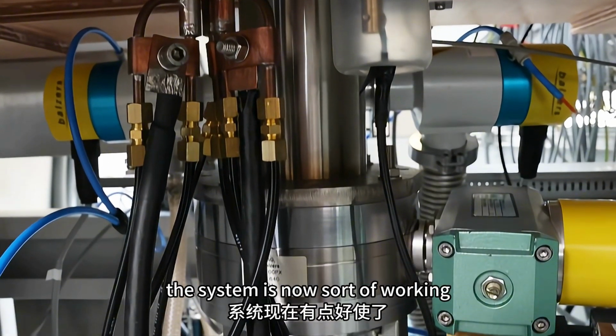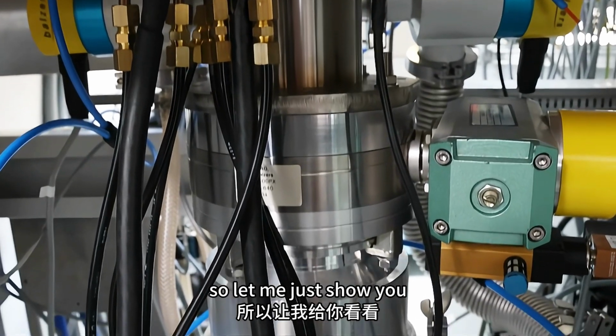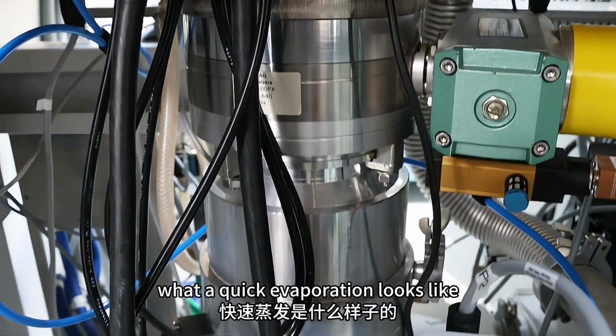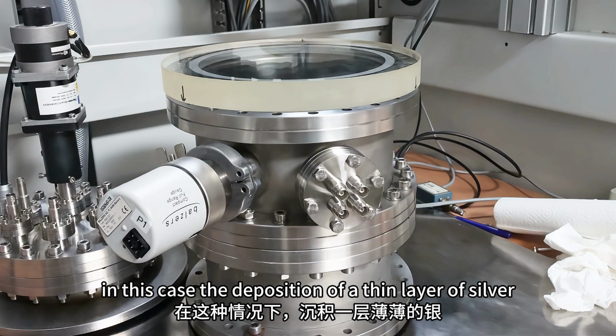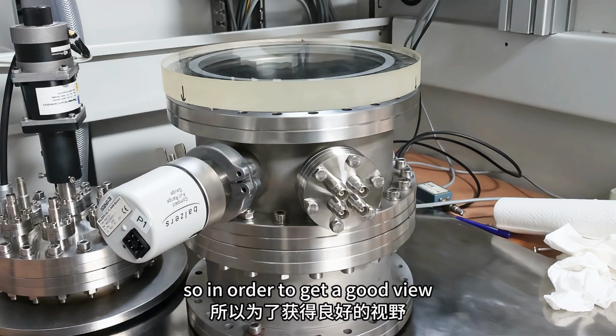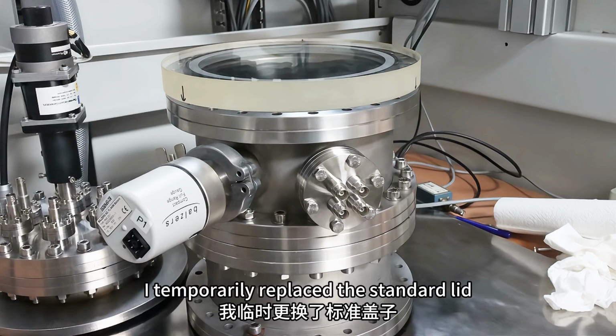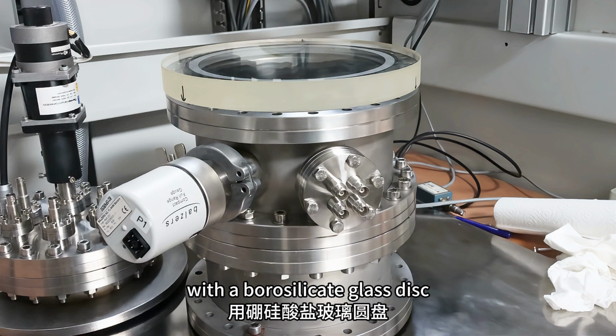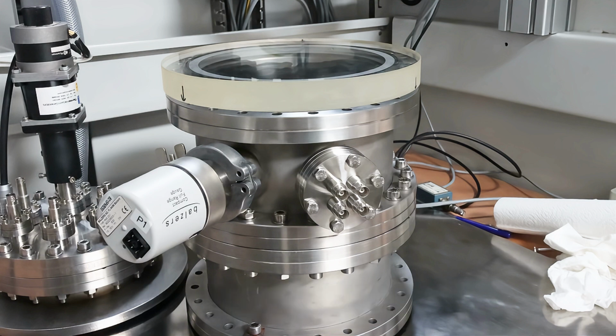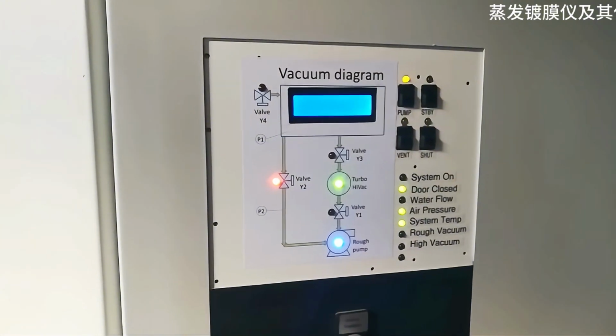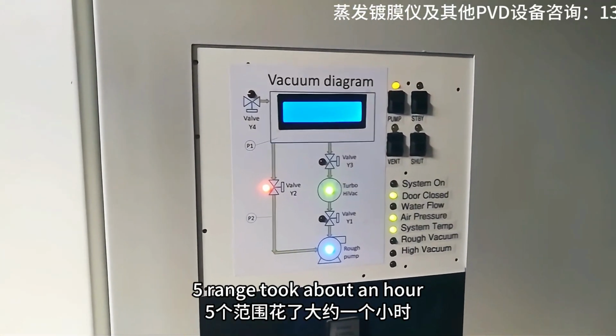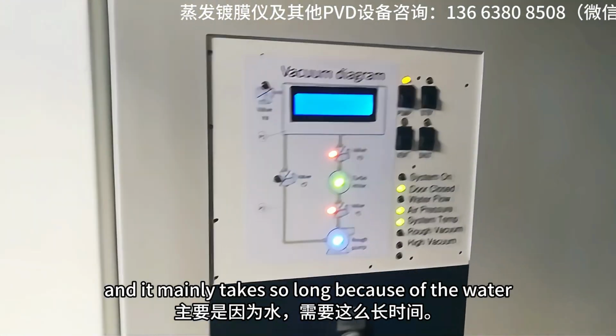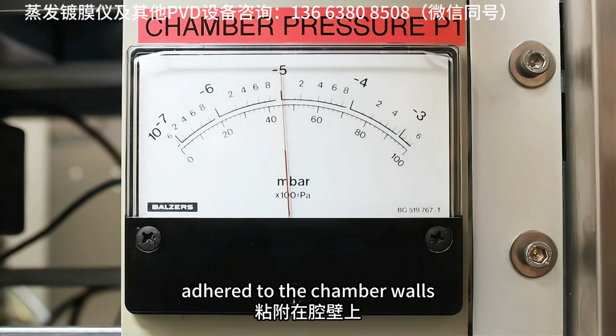The system is now sort of working, so let me just show you what a quick evaporation looks like. In this case, the deposition of a thin layer of silver. In order to get a good view, I temporarily replaced the standard lid with a borosilicate glass disc. Pumping down to the 10E-5 range took about an hour, and it mainly takes so long because of the water adhered to the chamber walls.